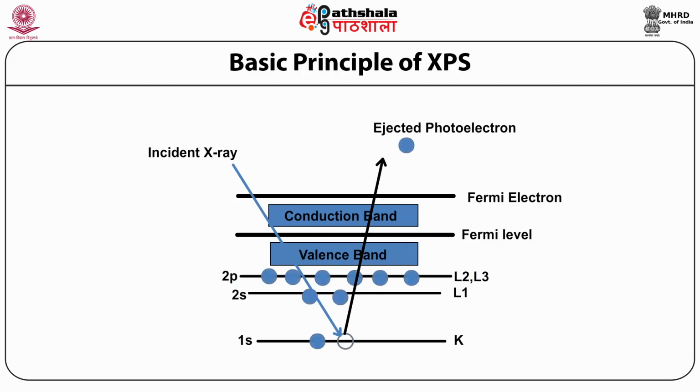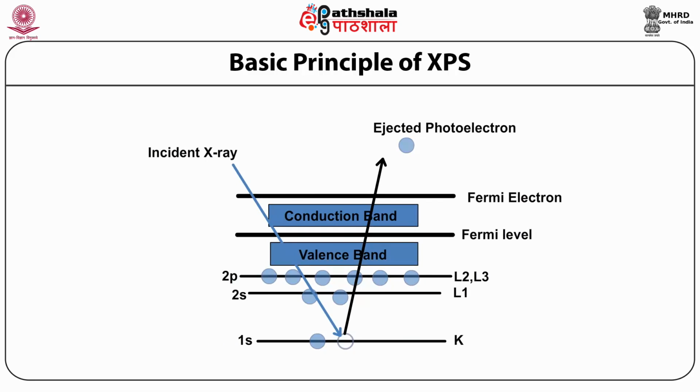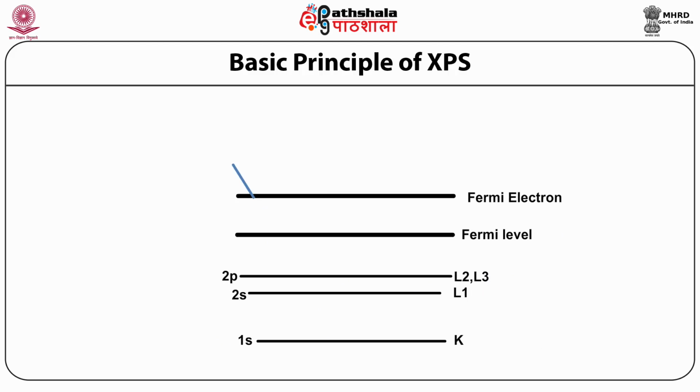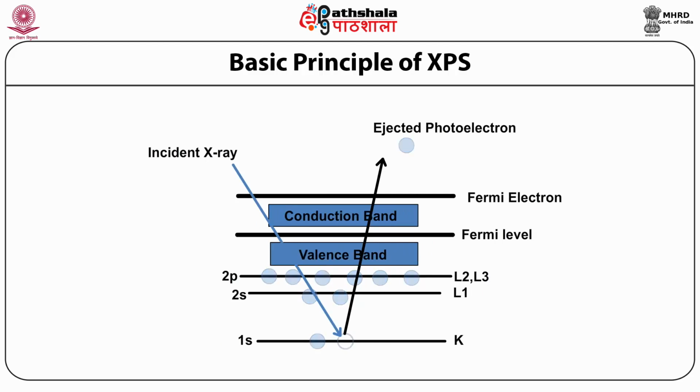The X-ray photoelectron is an electron ejected from an electron shell of an atom when the atom absorbs an X-ray photon. The value of phi depends on both the sample material and the spectrometer. Binding energies of atomic electrons have characteristic values. These values are used to identify elements.